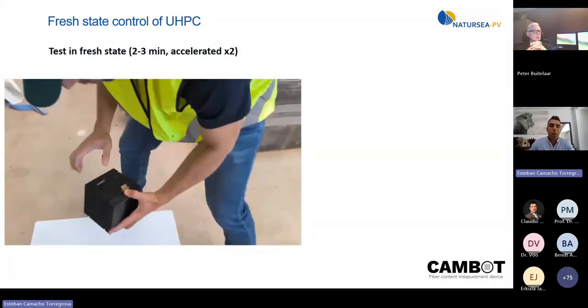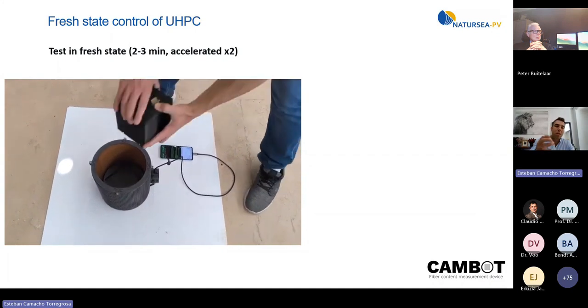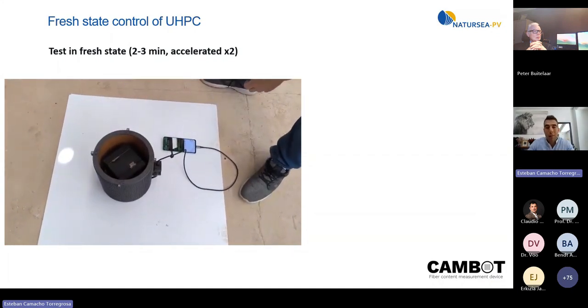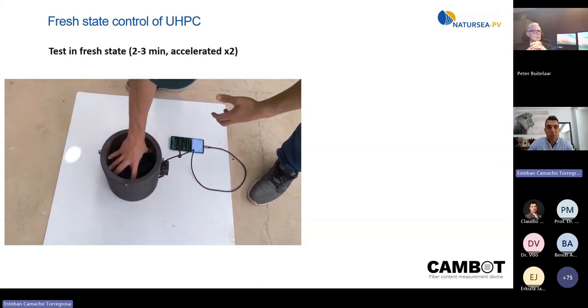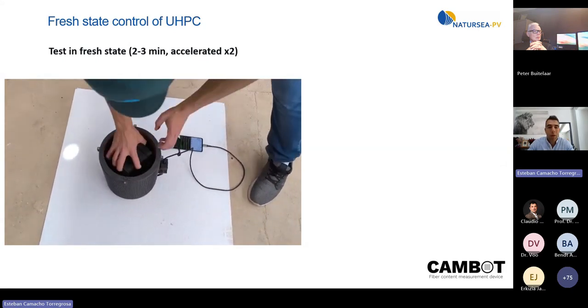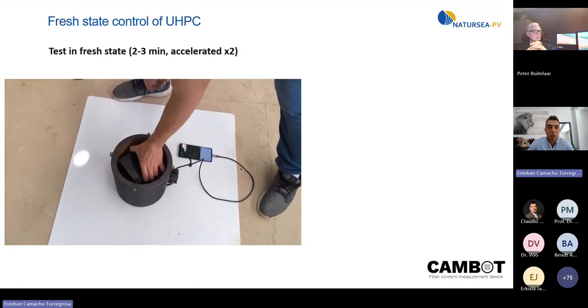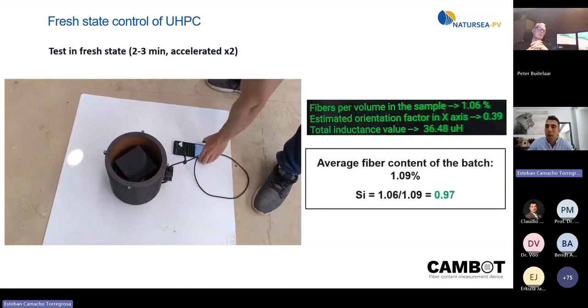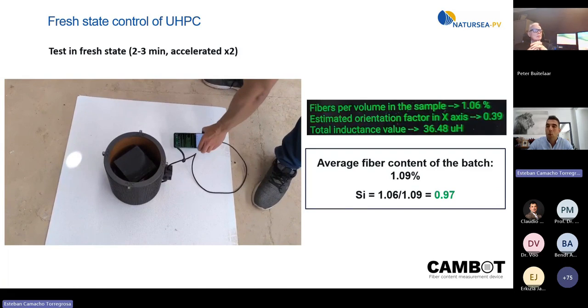As there is no air inside, the fibers don't change their position, and the value that we obtain after these 3 measurements estimates the fiber content of the mix. In our case, as you will see now on the left, this batch has 1.06% of fibers. The amount of fibers that we added to the batch on average was 1.09. So this was the last concrete that we were pouring, and the amount of fibers has decreased less than 3%. This means that we are not having segregation.